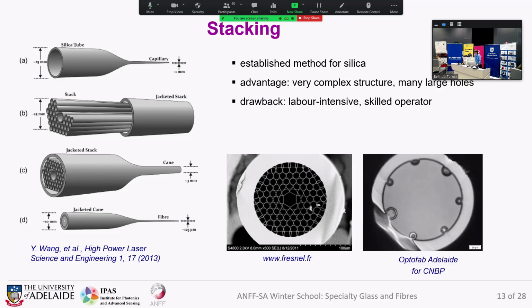We had a few trials 1-2 years ago. You see here the fiber made with this technique. We did 3 to 4 trials, and to make a really good fiber, I heard you need to make 100 trials. So we are now looking into getting the funding so that we can also do 100 trials, and then also make these hollow core fibers via the stacking technique.